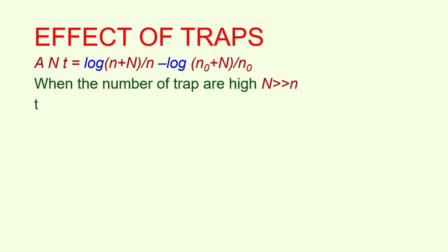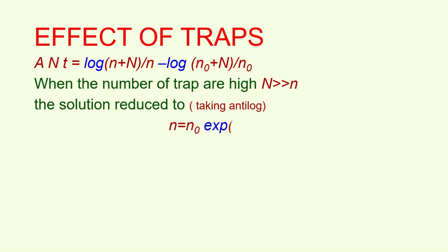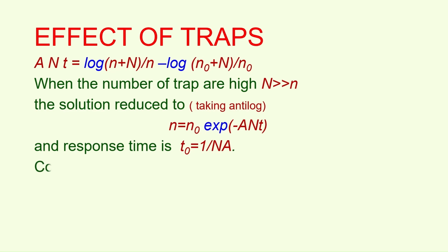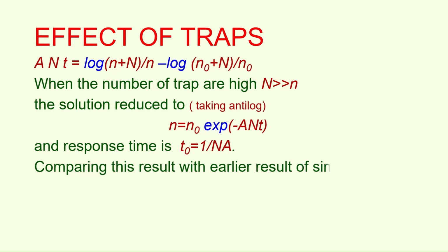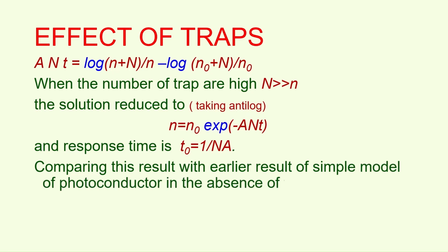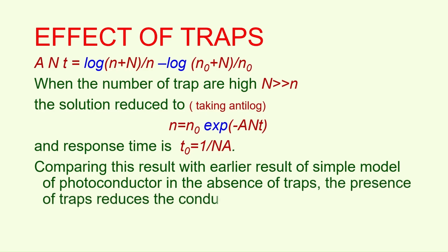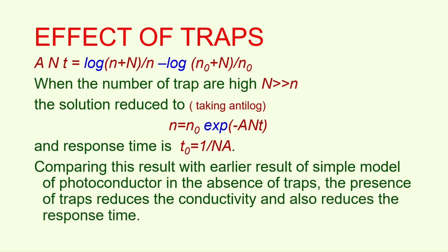When the number of traps is high, capital N is far greater than n. The solution reduces to n equals n0 exponential of minus A N t, and response time is t0 equals 1 divided by N A. Comparing this result with the earlier result of the simple model of a photoconductor in the absence of traps, the presence of traps reduces the conductivity and also reduces the response time.